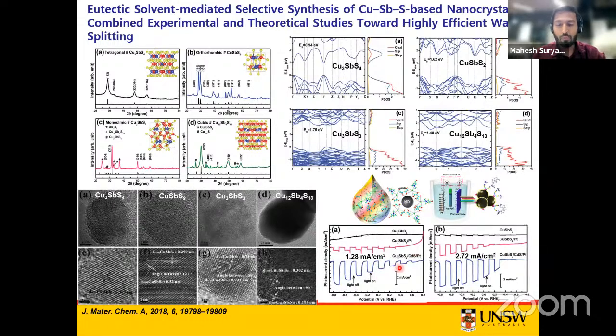So what we did is we incorporated the n-type CdS layer in between this platinum and this absorber material to form the PN junction. The intention to form this PN junction is to improve the charge separation by utilizing the benefits from these PN junction heterostructures. And we saw a drastically improved photocurrent density of about 1.28 milliampere per centimeter square for Cu3SbS4/CdS/platinum, and about 2.72 milliampere per centimeter square for copper antimony sulfide, that is CuSbS2/CdS/platinum.